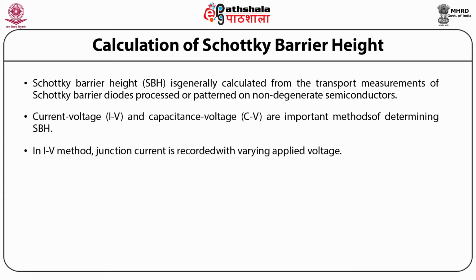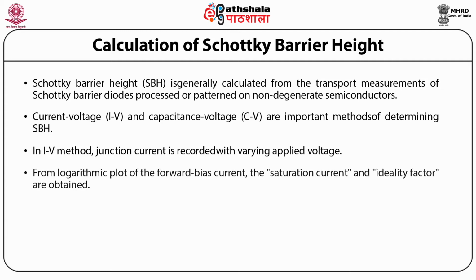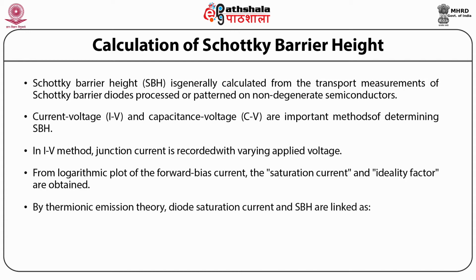In the IV method, junction current is recorded with varying applied voltage. From the logarithmic plot of the forward bias current, the saturation current and the ideality factor are obtained. By thermionic emission theory, diode saturation current and SBH are linked as I_SAT equals A times A star times T squared times exponential of minus phi_BN divided by k_B T. This is represented as equation 4.